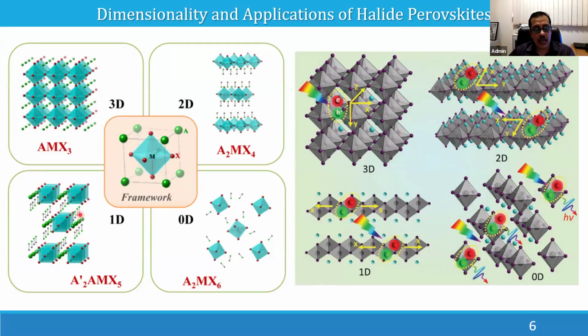We can still play around with the organic cation. You can use a slightly bigger or branched structure. In that case, again, it will force the inorganic building blocks to pack in only one direction. Instead of 3D or 2D, the octahedrons pack in only one direction, and it will further confine the exciton. The quantum confinement effect will start playing, but the exciton can still travel along the X direction, left or right, but not in the Y or Z direction. So this is a one-dimensional material, and the last one is a zero-dimensional material.